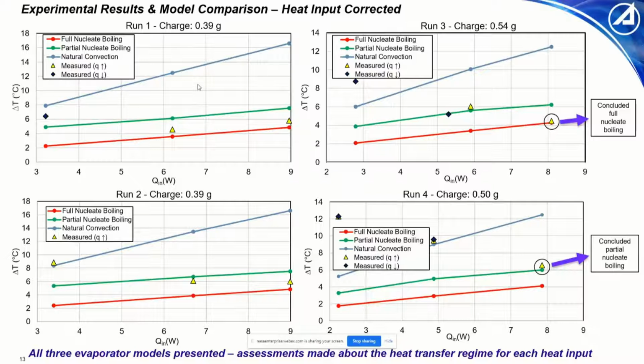Across these runs, the model curves remain more or less the same, differing slightly due to different working test temperatures—that TW constraint changes. But the experimental values show a very wide range in the results.